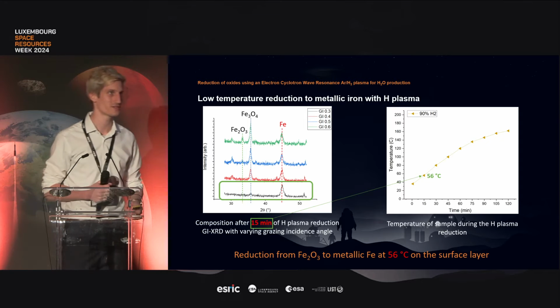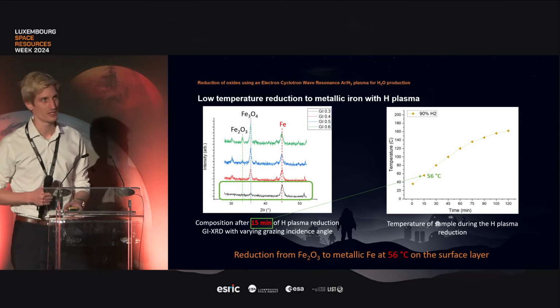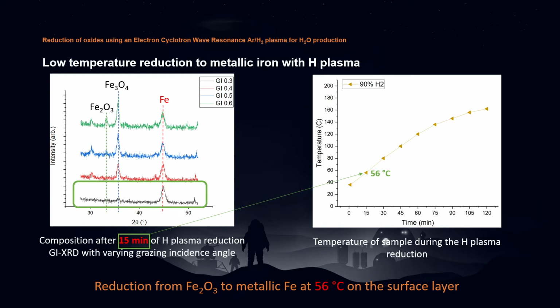We're going to dive a little bit into graphs. On the left, we are looking at the XRD with varying grazing incidence angle. It's a sample that has been treated for only 15 minutes with hydrogen plasma. We're focused on the black line spectrum, and we see that we have a peak of metallic iron. We also know that plasma during that time naturally heated the sample up to 56 degrees, which indicates that we are able, on the very surface layer, to reduce the Fe2O3 down to metallic iron at only 56 degrees.